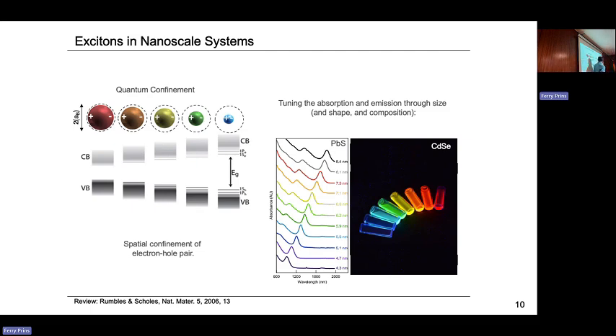And with that, you can control, for example, the absorption of your solar cell, matching it exactly to the spectrum of the sun. While in conventional semiconductors, there are only so few types that we have that already have their band gap fixed. We're very lucky, by the way, that silicon is the most abundant material we have, and it happens to fall exactly at the peak of the solar spectrum. It's one of those coincidences of nature that we couldn't have predicted better, but here you have the flexibility to actually tune the band gap.